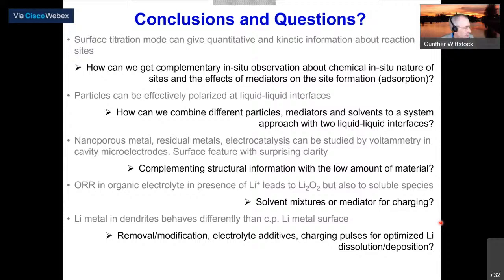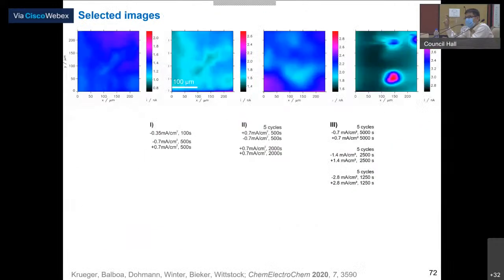So we started doing it at macroscopic interfaces, but then it's much more difficult to make the approach. That is much easier with the pipette because we can observe them with a microscope and determine very precisely the distance towards the microelectrode. That is the main advantage of using the pipette configuration. For a device, of course, one would like to have macroscopic surfaces, maybe even emulsions. Now, in that pipette kind of electrode, is there any possibility of accumulation of nanoparticles suspended in the solution in the smaller part of the pipette rather than the bigger part of the pipette?